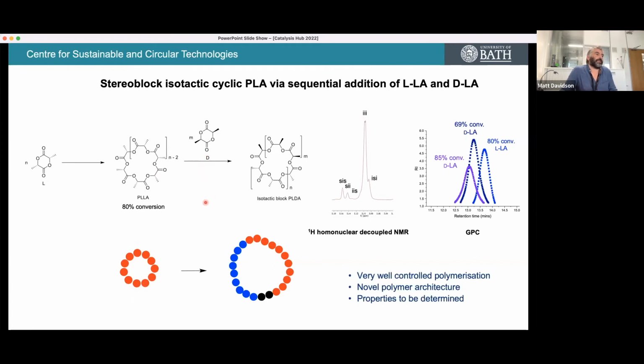So what we would expect is that the remaining L-lactide will preferentially polymerize with the D to use up the remaining L in an atactic or slightly heterotactic block, a small block of atactic or slightly heterotactic PLA there. And then from that point, there's only D left, so you get an isotactic block. So essentially, we've got a stereoblock, diblock isotactic PLA here, probably with a small atactic bit that mops up the remaining L-lactide monomer. That's what we think we're seeing with these signals here from the homonuclear decoupled NMR.